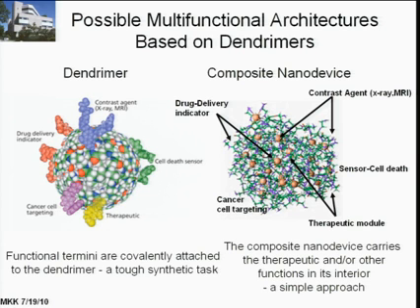What the composites open up is the ability to put some of that functionality within here. You could have inorganic materials such as gold that may be useful for SPECT imaging or may be useful for delivery of radiation therapy. You can have other types of isotopes within here. You can have gadolinium that can be trapped within these devices. So this composite nature, allowing you to trap, opens up more degrees of freedom for the chemical reactions, to allow you to truly build what we'd like to have, which are multifunctional platforms. Platforms you can modify slightly and tailor to carry out many different functions and carry out multiple functions.